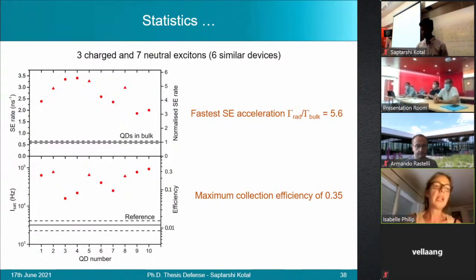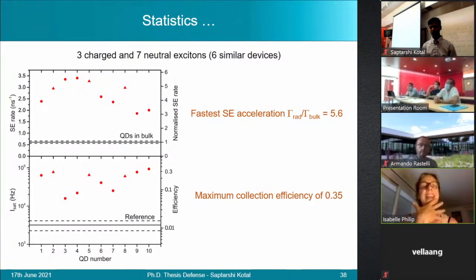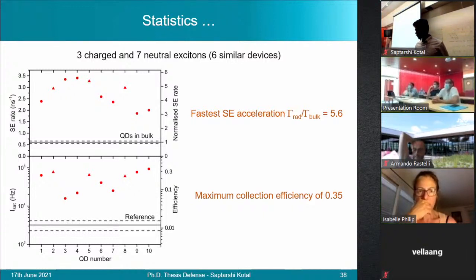Because, for example, on the spontaneous emission rate, we see that we have almost no error bar. It's roughly about 0.6 per nanosecond for all the dots, but you have a bigger dispersion in the case of the dots in cavities. Is it due to position or something else? It could also have to do with the number of measurement points that I had to make the average. But predominantly, yes, the deviations I would associate to the differences in position.